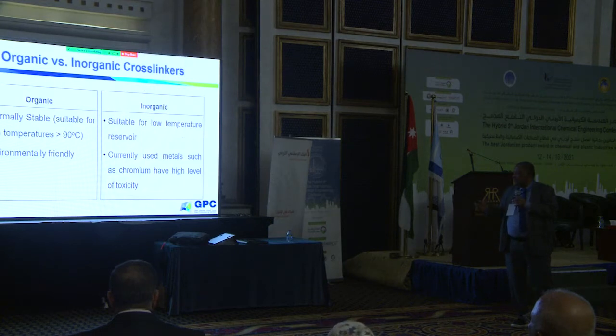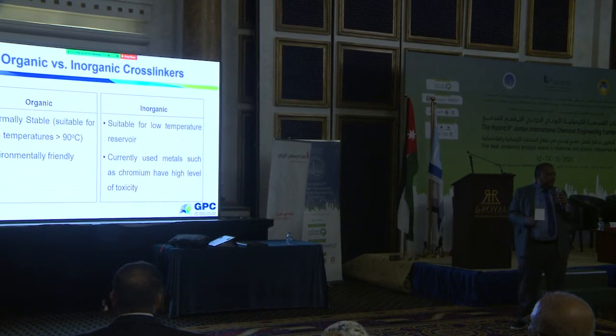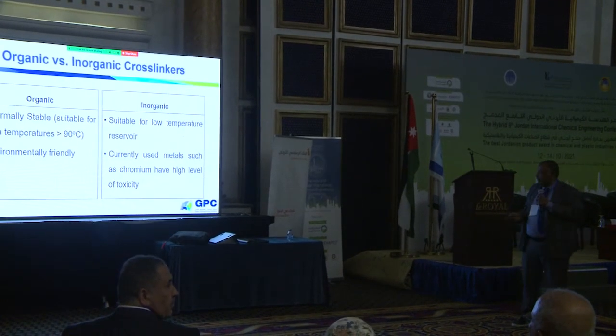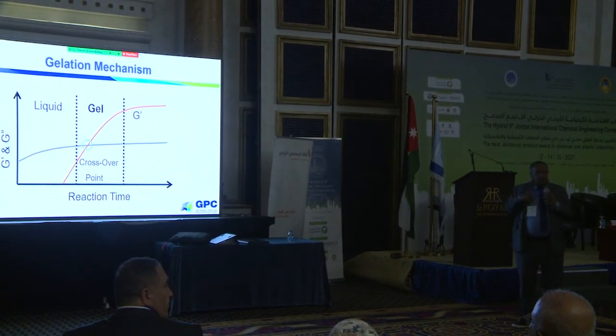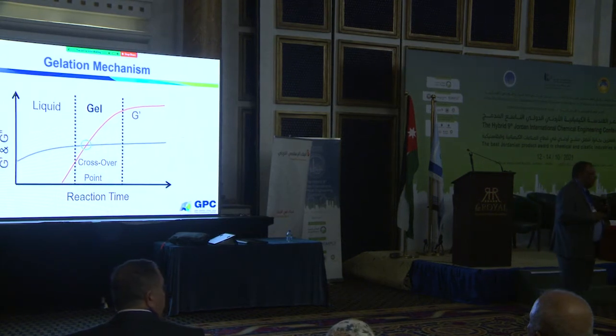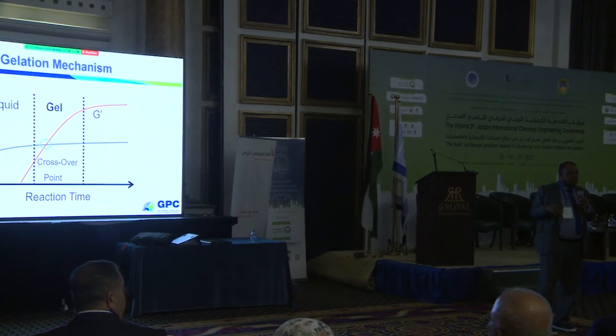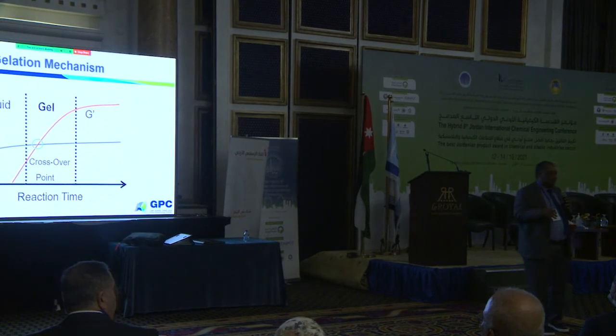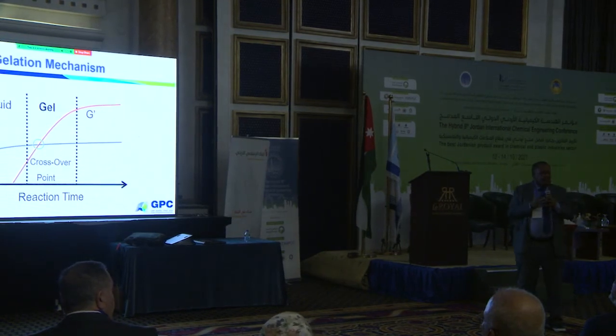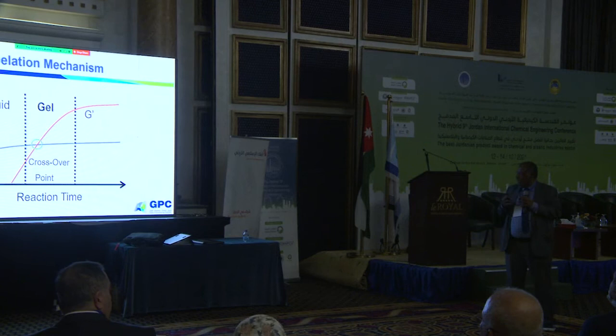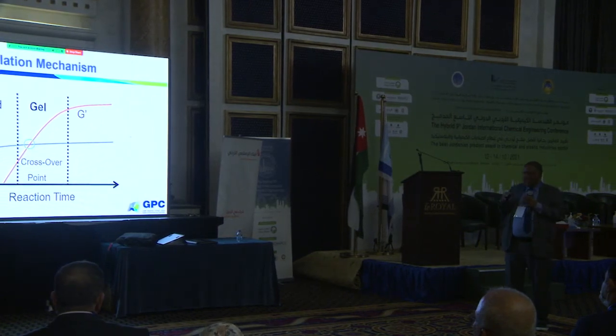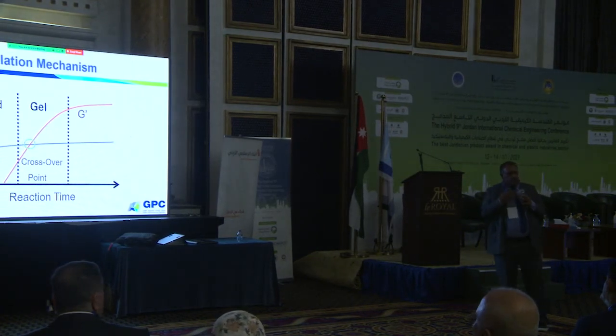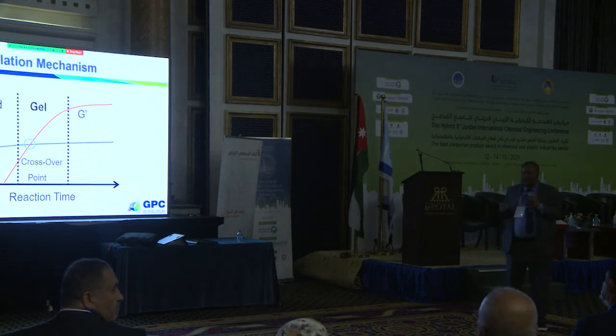The advantage of these organic and inorganic crosslinkers is that they are stable, but as I mentioned, the organic ones need high temperature. The inorganic ones have problems of toxicity, especially chromium, which is widely used. When we call this material a gel, we measure something called G prime in rheology. This is the elastic modulus. Once the G prime is higher than G double prime, that means it is more solid than liquid, and we call that a gel.